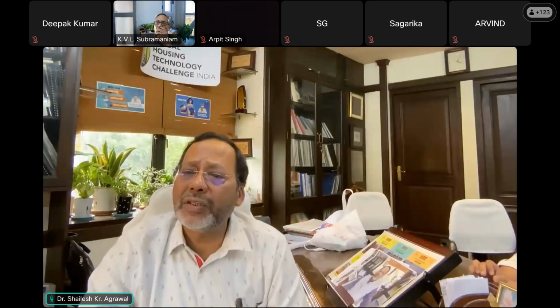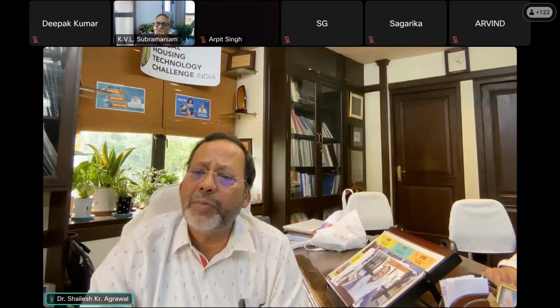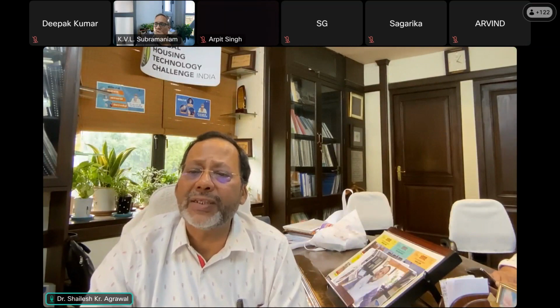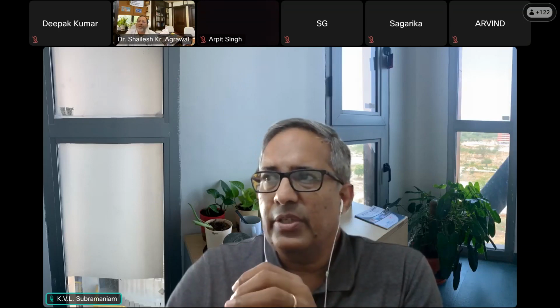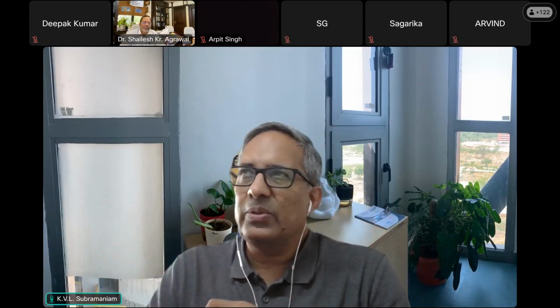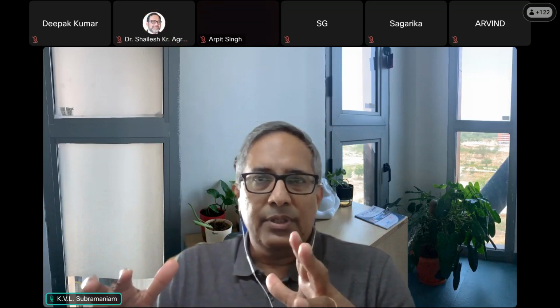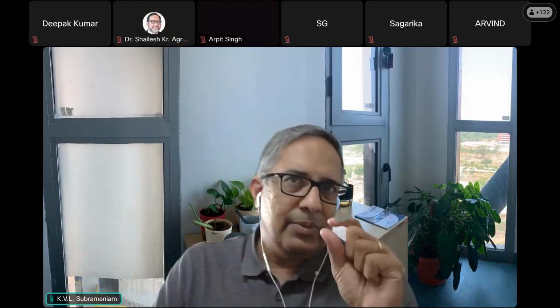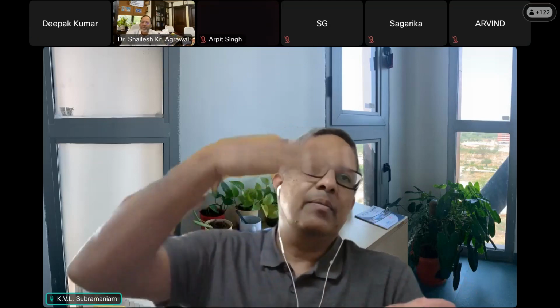Sir, another one is, how much time interval is being maintained between two consecutive runs of placing layers one over the other? I'm not sure if that showed up in the video, but in the bridge video that you saw, each segment has two halves. Each segment was printed over 2 days. Each segment itself, I think, took about 3 hours to print. Now the nozzle itself moves very fast. Each layer was about 15 millimeters in thickness, and one layer was completed in a span of 40 seconds. So roughly, that's about the time interval that you have between multiple layers.